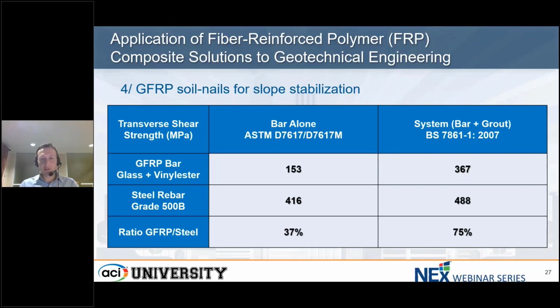What's very interesting with the results is on the second column in the middle, bar alone, you can see that a GFRP bar would only develop about a third of the steel bar when tested for pure shear, so the dowel effect, which is consistent with the perception that GFRP is weak in shear, and also that it's easy to be consumed by excavation equipment, tunnel boring machine. However, when you test it as a system with the surrounding material, the performance of steel increases marginally. You see from 416 MPa to 488 MPa, but the performance of the GFRP bar more than doubles. And for this reason, the GFRP bar would develop 75% of what you get from a steel bar.